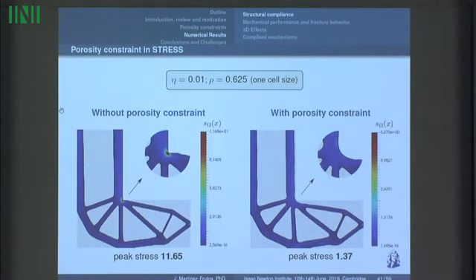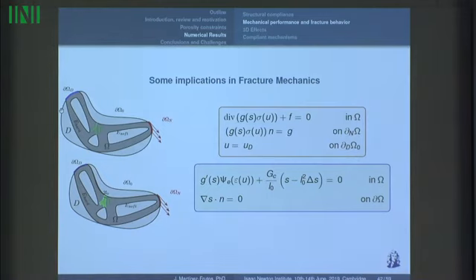Now what we want to do is to analyze all these designs against fracture. To do that, before analyzing these designs, I want to introduce some notation about the simulation we are going to do. We are using a phase field method. What the phase field method does basically is to smooth a sharp crack surface by introducing a parameter S, which is the phase field parameter, and also an L0 parameter, which is a length scale parameter. As customary in phase field methods, we have two coupled PDEs. The first PDE is related to the mechanical problem, and the second PDE is related to the evolution of this phase field parameter S.